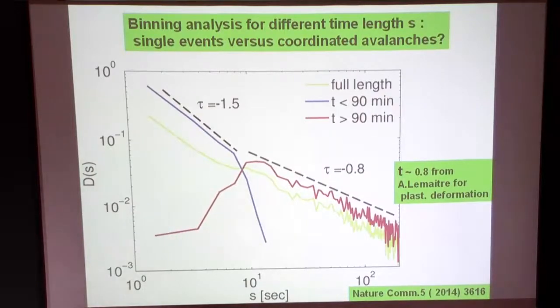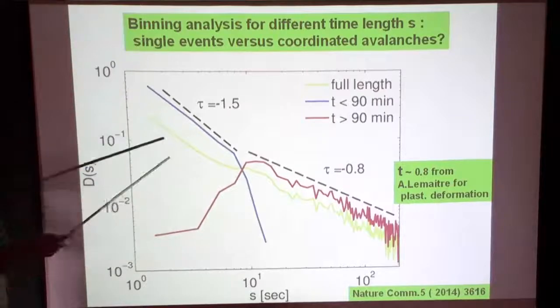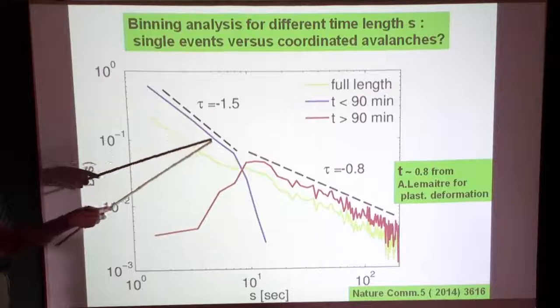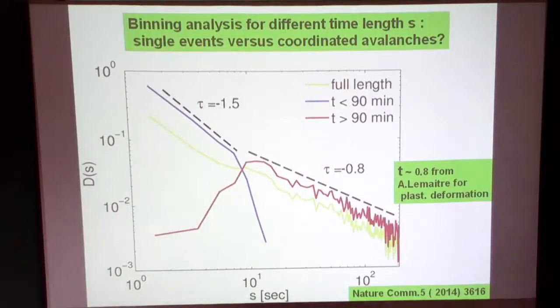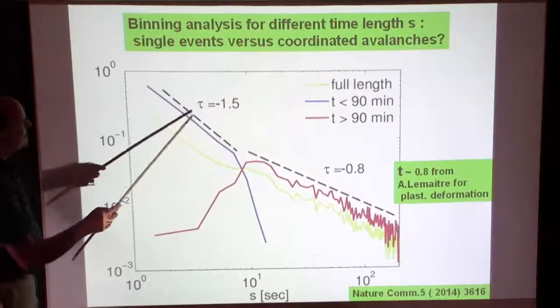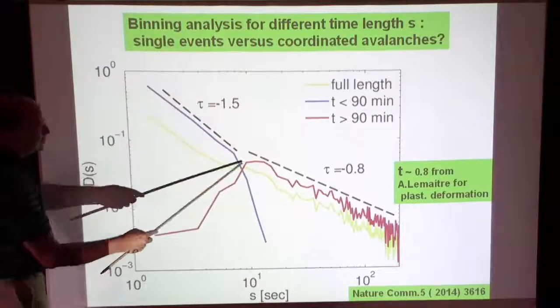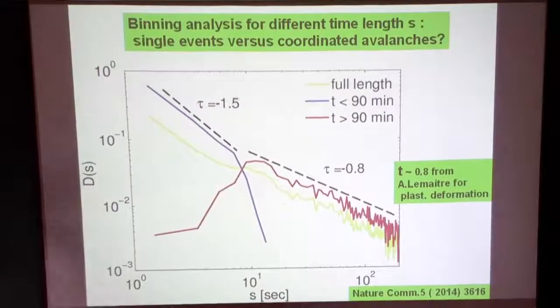So it's a mixture of mechanical excitation and thermal excitation. And what we believe, what we see actually is, which is a debate, we can discuss it. I'm happy to get other numbers and other ideas about it. We see here in the mean field idea, we have all these local events, our 50 nanometer events, which take place more or less randomly. And then we need something which coordinates that into a shear band. We need something, these quadrupoles, which are lining up. We have somehow to align these up with a certain critical density maybe, which then make a 2-dimensional shear band. And what we discuss here, it's open actually, I make a question mark behind that, is that from these single little shearing events, we cross over to a real shear band, to a nano shear band, which has then a different power law.